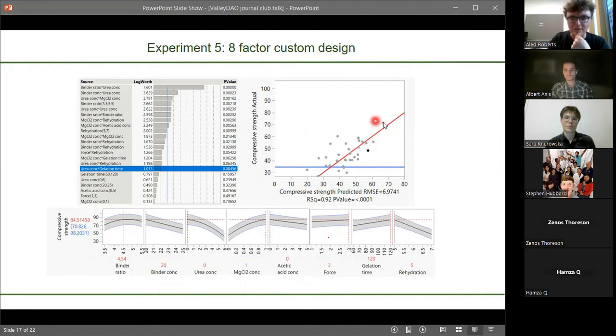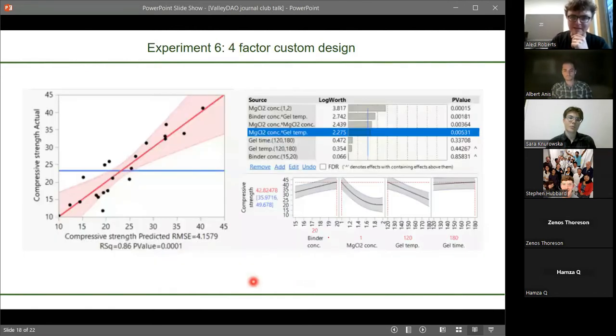And one of our samples was over 70 megapascals under compression. So it found one random combination which was a really nice area of the experimental space. We got a very strong material out of that.